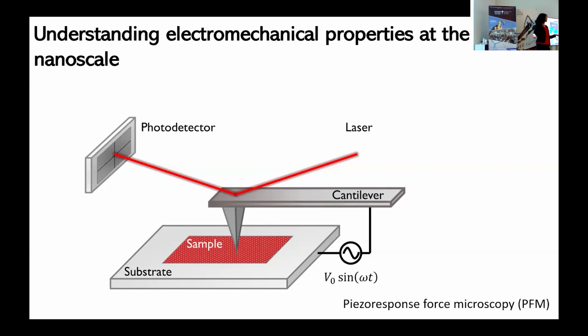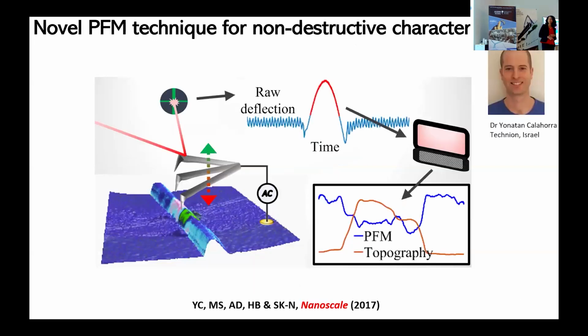And I'm talking about soft polymers. They don't really go. Also, I'm working with nanowires or individual nano objects. And this is a contact mode method. You have to have contact, and you're scraping this tip across this soft sample. So you end up either displacing or destroying the material. So it's quite tricky doing PFM on polymers.